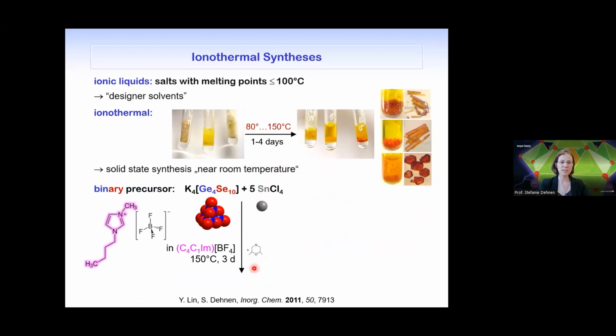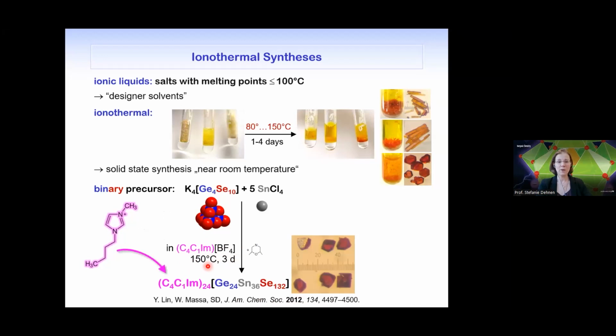And in this particular case, when we used these reaction conditions, 150 degrees C, so this is a reference to our very first paper in this field, but under slightly varied conditions, we received a compound with this composition. And you see that the imidazolium cation went into the compound, so it replaced the potassium ions used initially. This is very important and instrumental to this chemistry, that the ionic liquid cations play a role. It's not just a reaction medium, it's also a reactant. And these were nice red crystals, which turned out to have this crystal structure here.